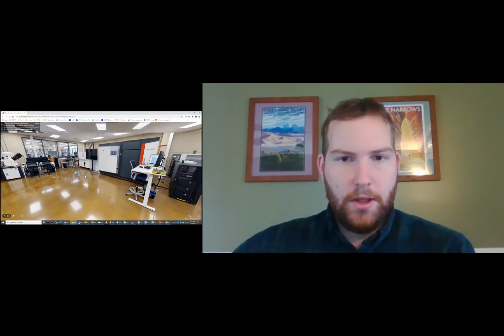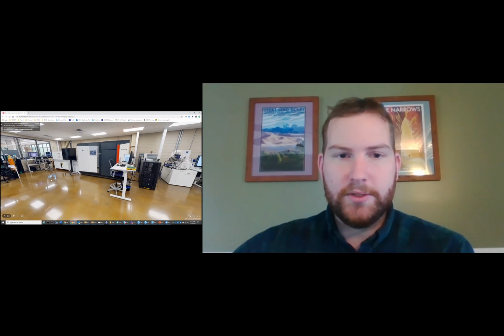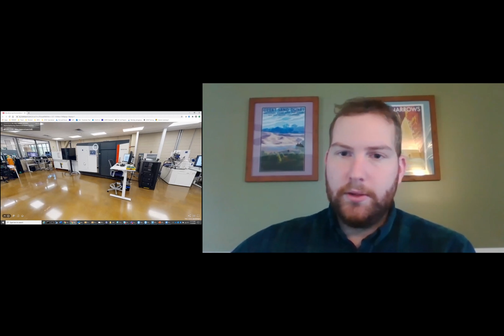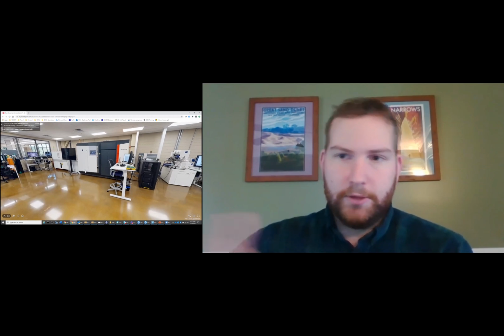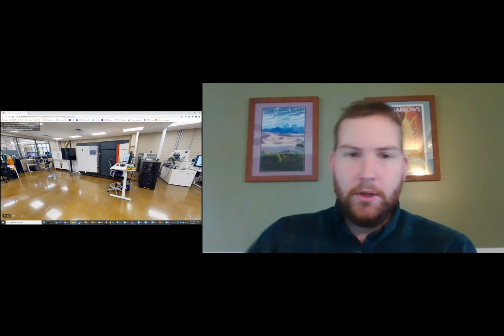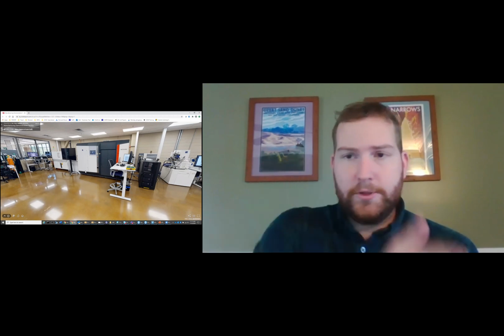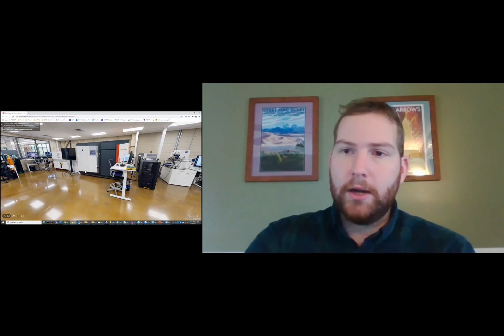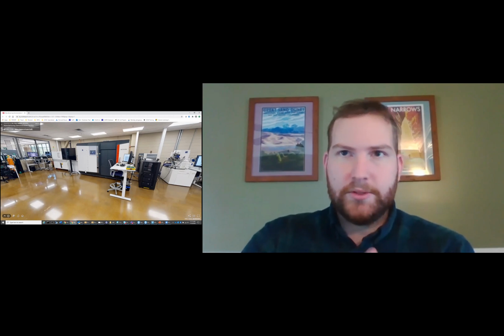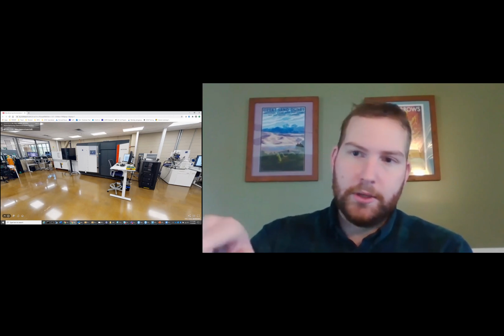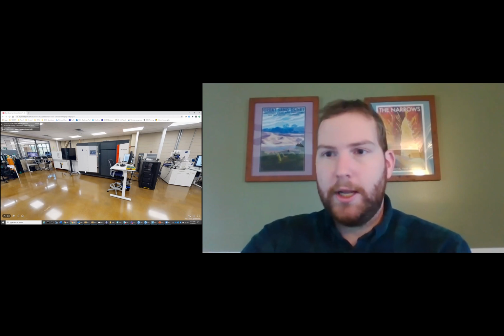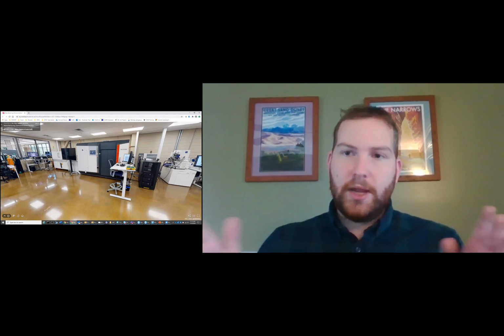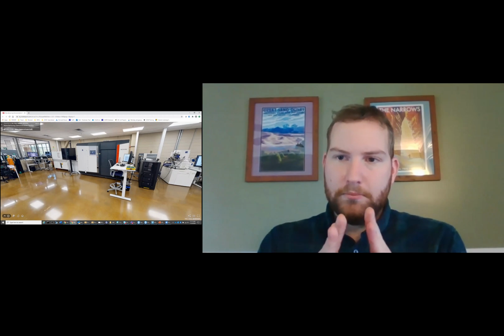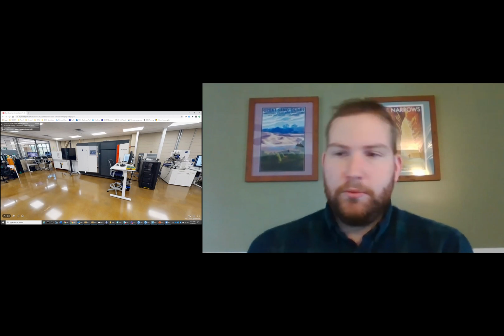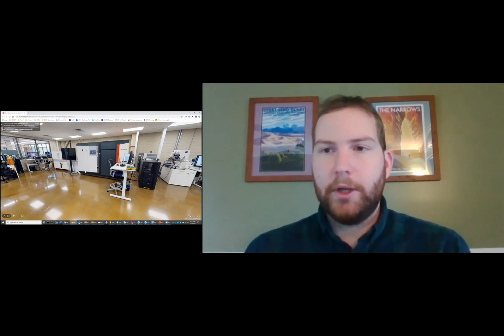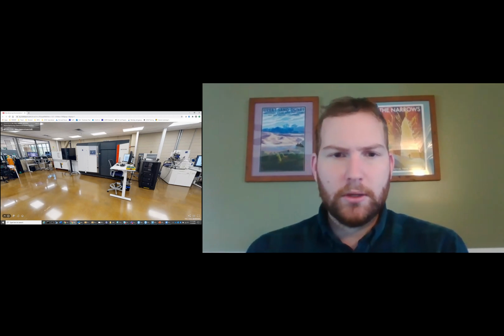So the benefit to having these together is that where the Metrotom leaves off in resolution, it stops at about 7, we can take that part to the Versa if we need to look at it at even higher resolution. That system starts at about 10 microns, then it goes down, like I said, to 300 nanometers. And of course, the size of the image that you're looking at each time is shrinking.